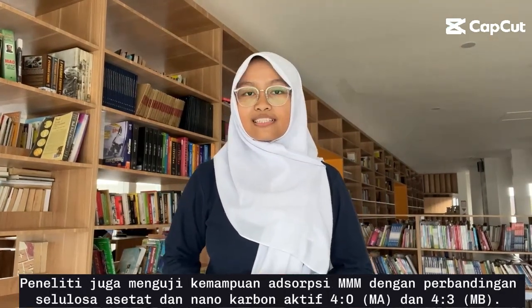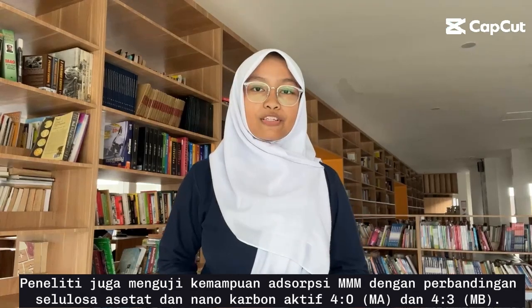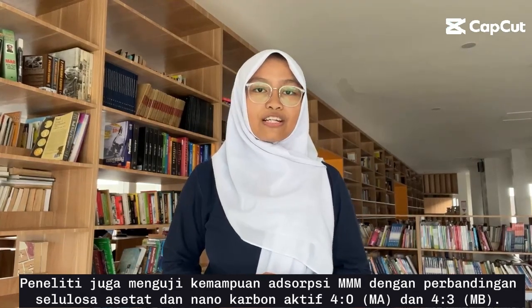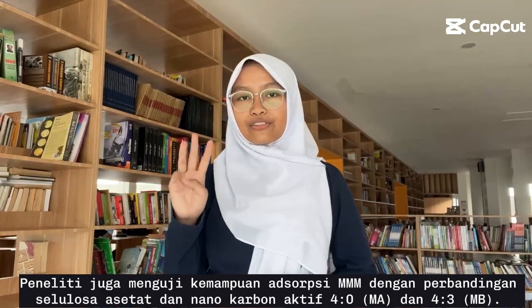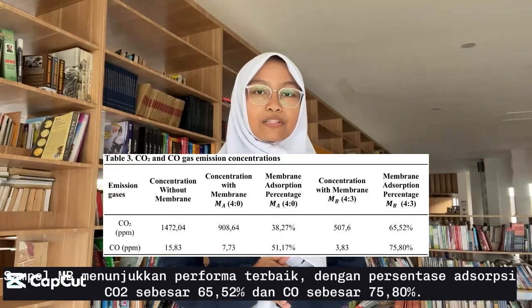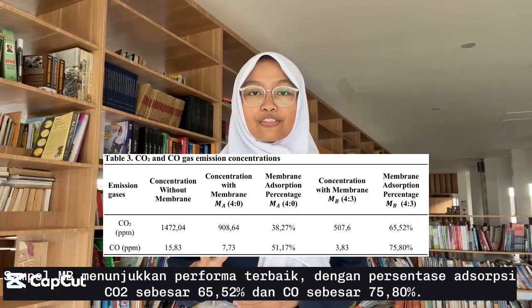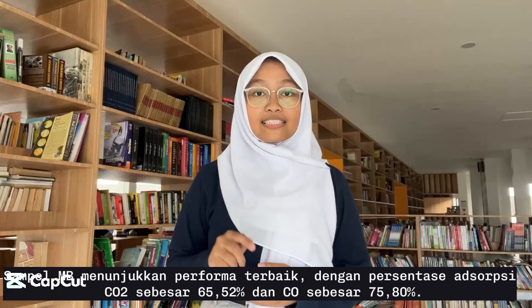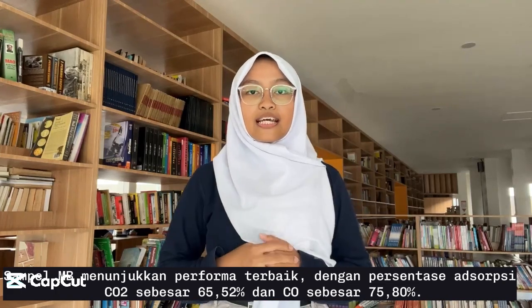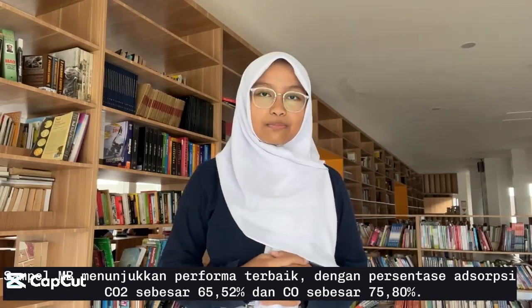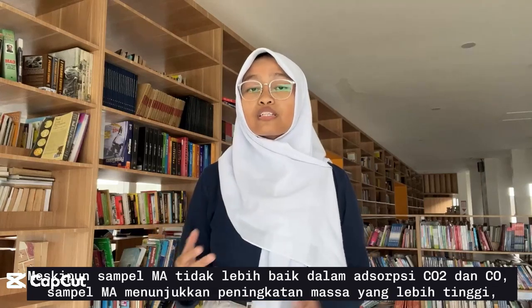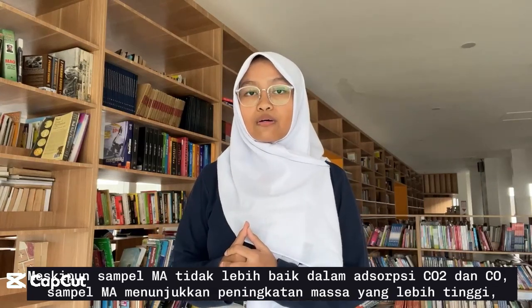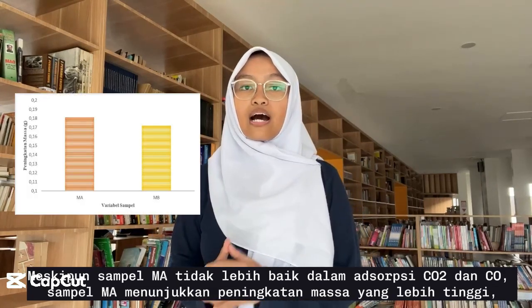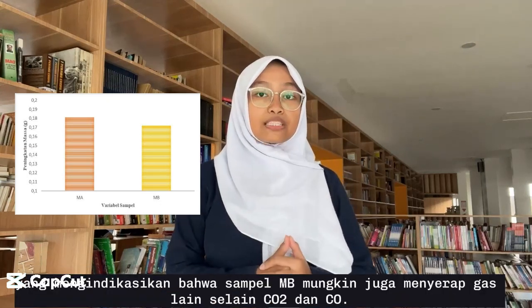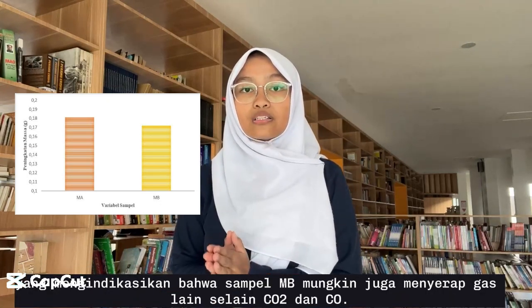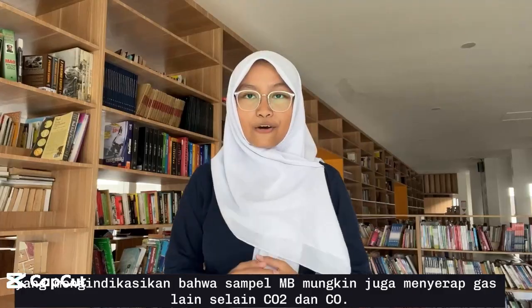The researcher also tested the absorption ability of MMM with cellulose acetate and nano-activated carbon ratio of 4:0 and 4:3. The MB sample showed the best performance, with a CO2 absorption percentage of 65.52% and CO of 75.80%. Although the MA sample was not better in CO2 and CO absorption, the MA sample showed a higher mass increase, indicating the sample may also absorb other gases besides CO2 and CO.